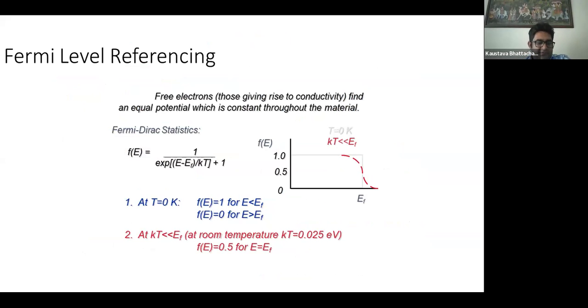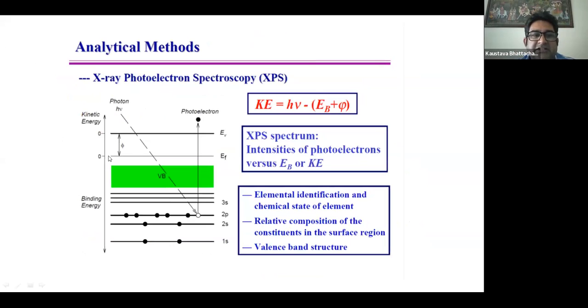Okay, so now we come to Fermi level referencing. If we look back to the last figure, this is my Fermi level, the energy of my Fermi level. If I know exactly the energy of my Fermi level, I can reference the material with it, and I can find out my valence band potential, because the next energy level after the Fermi level will be my valence band. So this EV we cannot find directly from the XPS, but definitely we can find the Fermi level. And as we can find the Fermi level, we can also find the valence band potential, or the valence band energy, from the XPS.